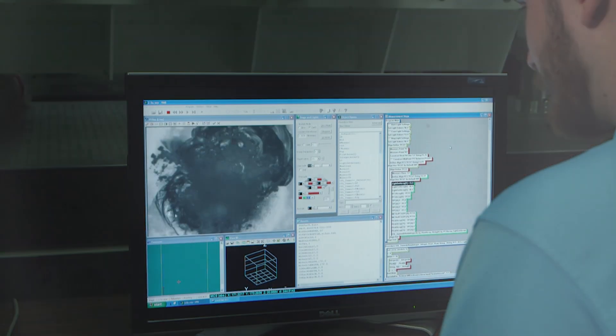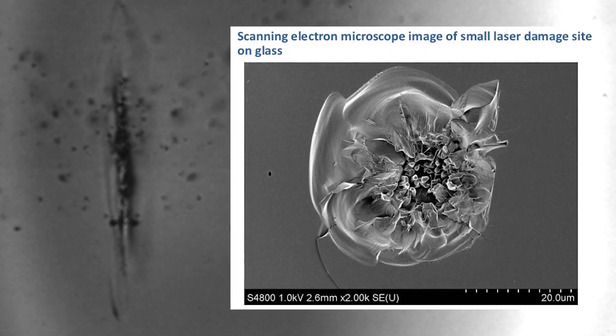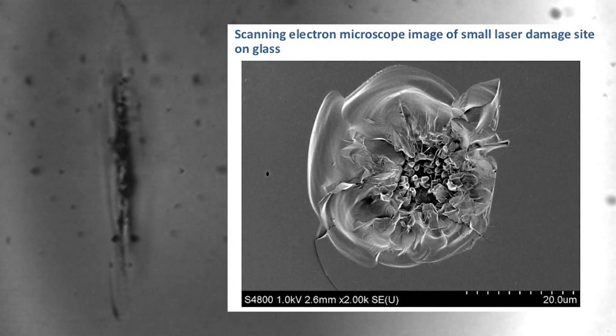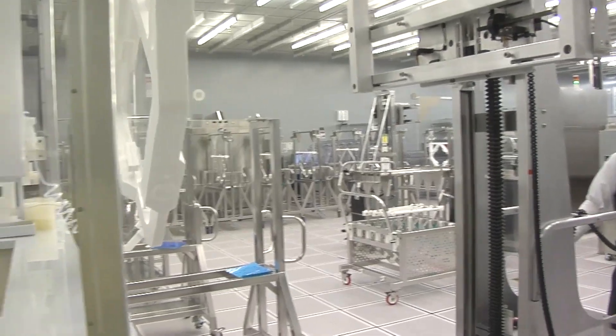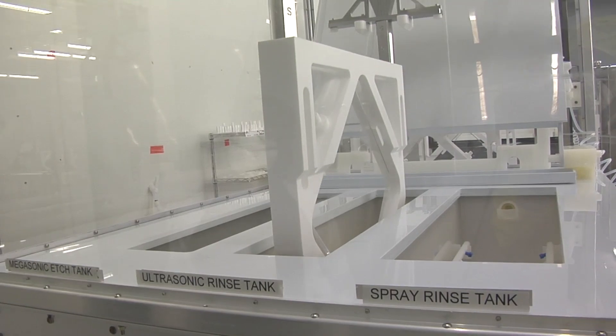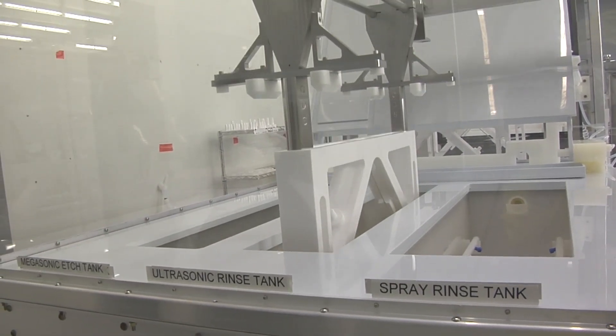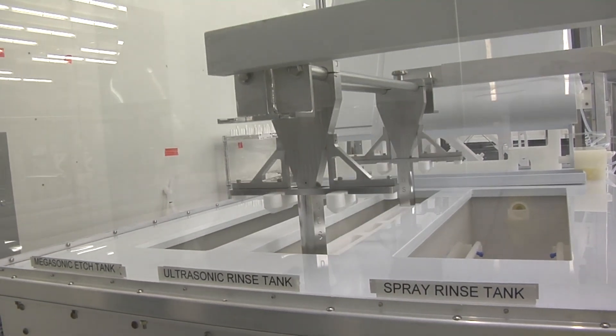We do this to guide development and use of our laser systems and ultimately to push the lifetime and performance of the optics. One of the most important recent successes was the discovery of the absorbing precursors on fused silica surfaces. To treat these precursors we've developed a chemically-based post-process, the advanced mitigation process or AMP, to essentially eliminate damage at UV light.